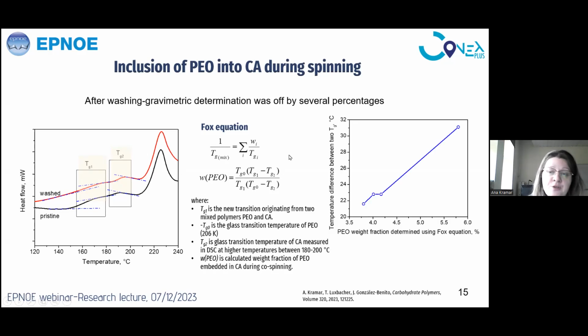And this temperature difference between the two Tgs corresponds to a certain weight fraction of polyethylene oxide, which was determined using the Fox equation. We found that it's corroborated with gravimetric measurements, and we presume that we actually have included polyethylene oxide into cellulose acetate.